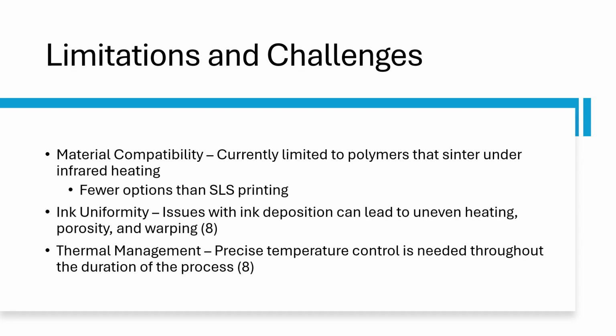Right now, high-speed sintering is limited to polymers that respond well to infrared heating, so the material library is smaller than that of selective laser sintering. Ink uniformity is critical. Uneven coverage can cause porosity or warping. Thermal control is also demanding. The entire chamber must stay within a few degrees between the recrystallization and melt temperatures mentioned earlier to maintain part integrity.